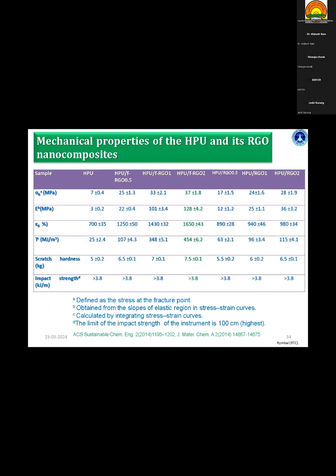Now, when you incorporate this nano reinforcing agent, particularly a functional nano reinforcing agent, in an amount, as I told you, less than 5%. Here we have used 0.5, 1 and 2% reduced graphene oxide, functionalized, and the functionalization is done in such a way that it will become part of the polymeric system. Here, bio-based castor oil-based hyperbranched polyurethane is used, and if you see, compared to the virgin polymer, this system shows improvement of almost 5 times in strength, toughness, scratch resistance, impact strength, and significantly the elongation at break.